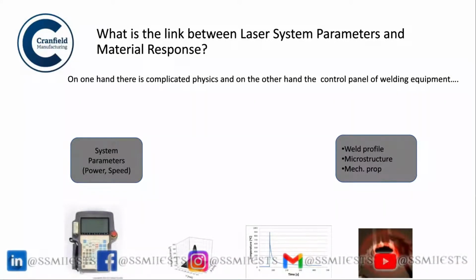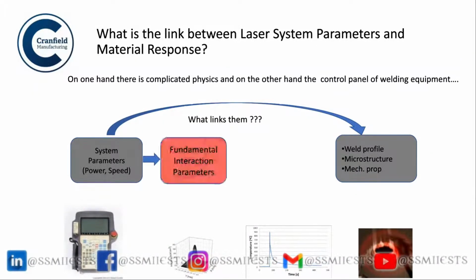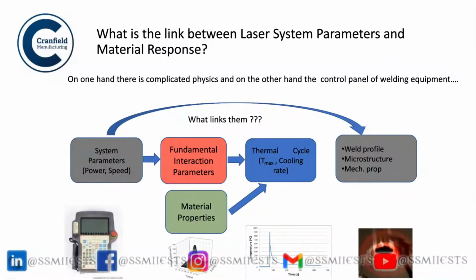And this is a work that was done in our place 2 years back, and this is mainly in the area of hybrid laser arc processing. So you can see here there are system parameters which has a speed, and then there is the weld profile. So what links them is basically fundamental parameters, material properties, which subsequently determines the thermal cycle and the cooling rate. So all these factors need to be controlled in order to achieve your desired weld.